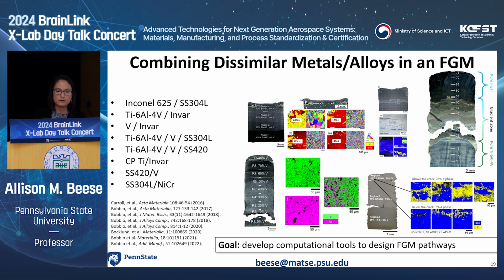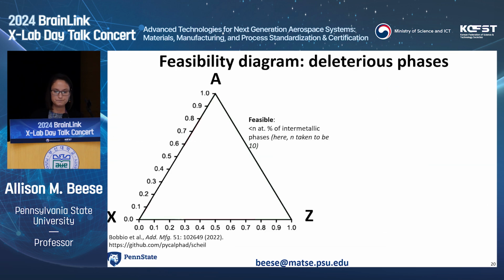So we've worked in this area for a while, and we were initially given a number of samples from NASA's Jet Propulsion Lab where they had graded between well-known alloys without sort of a design aspect. So the idea here was, okay, if you just blend well-known alloys, you're going to end up with cracking and failure due to the fact that you have intermetallics present. So our goal then was to say, well, how do we make sure that we can get from one composition to another composition without failure?